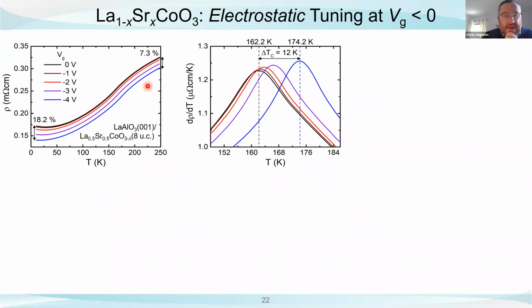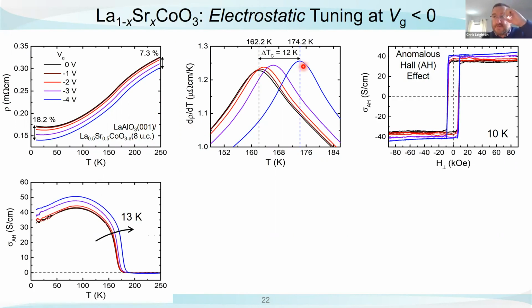It's quite small. And then there's also an inflection point in here that tells us about where the Curie temperature is in this material. So we can expose that just by plotting the derivative of d rho by dT. You can see that by applying -4 volts, we get about a 12 Kelvin shift in the Curie temperature. Now, if we measure the anomalous Hall coefficient, turns out this material has quite nice anomalous Hall conductivity, so we can also probe magnetism that way. We can measure the anomalous Hall conductivity as a function of temperature, as a function of voltage, and you can see here nice proof that we get about a 13 Kelvin shift in the Curie temperature.